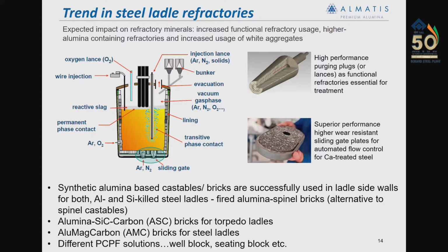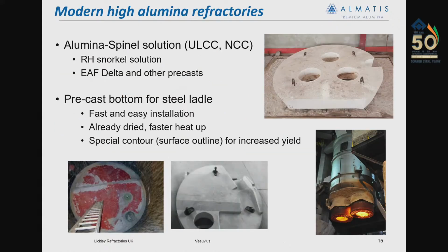High performance driven ASC brick, which is alumina silicon carbide carbon brick for torpedo ladle, AMC brick, alumina magnesia carbon brick for steel ladle, and different PCPF solutions, not just the application. There are a lot of things in material development also going on, which I shortly highlighted in my next slide, like ULCC and NCC based castable, and then precast in RH snorkel, delta precast, and all other things.